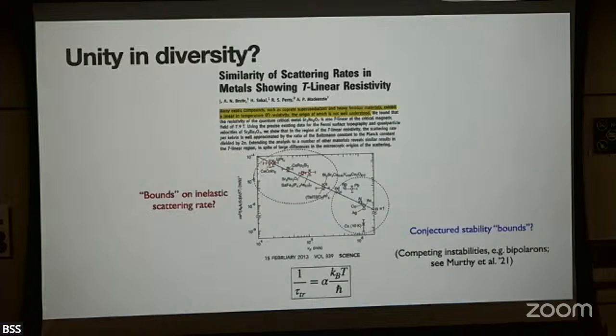All right. Right. So as I said, naive Matthiessen-type arguments would tell you that, the more scattering channels you add for electrons, the temperature dependence of the resistivity will keep increasing. And that doesn't seem to happen in at least two of these examples. Turns out that's also the case across many different unconventional metallic systems which exhibit linear resistivity. So this really was one of the main motivations for coming up with this idea that there might exist some fundamental bound on how large the scattering rate might be.